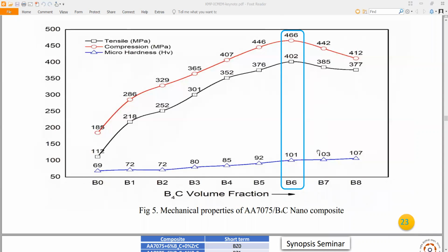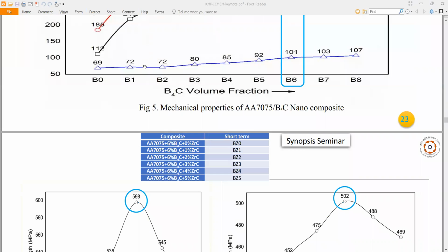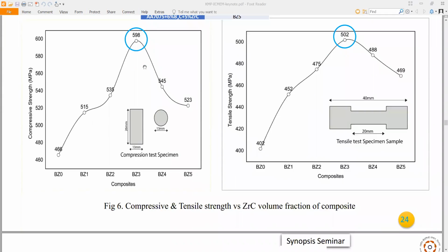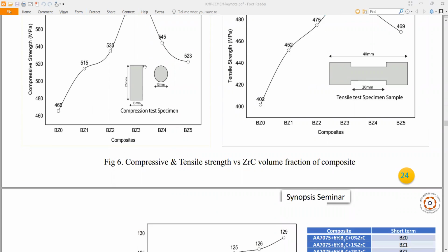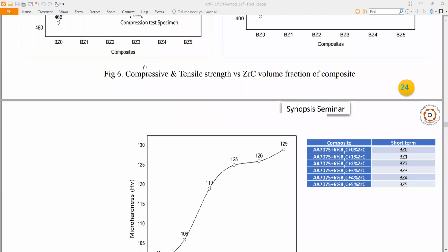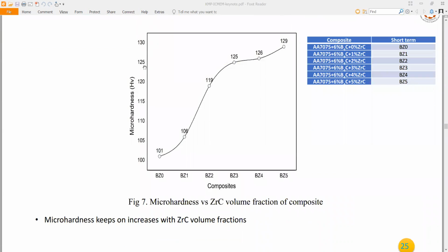Here we can see the volume fraction of B4C, and then tensile strength in the figures, then compression in MPa, and micro hardness also. This is shown with this green color. Here also these composites are shown, with compressive and tensile strength versus zirconium carbide volume fraction of the composite. This is the name of the composite, and this is about micro hardness versus zirconium carbide volume fraction of the composite.